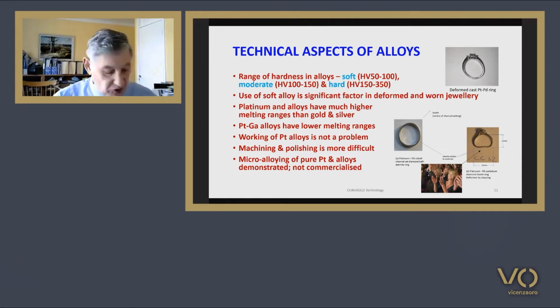Platinum tends to gall or adhere on the tool. The low thermal diffusivity of platinum alloys makes welding easier, particularly laser welding, compared to gold and silver alloys.